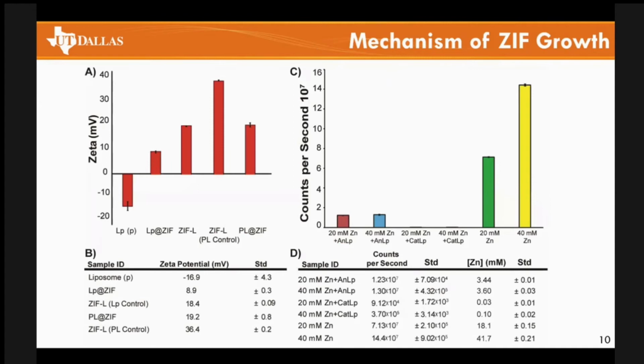Okay. So the next question that we wanted to address with this project was, okay, we have shown that we can easily encapsulate these materials in the ZIF coating, that they are indeed protected. However, we wanted to determine what exactly was promoting the ZIF growth around these materials. So we ran zeta potentials and ICP-MS, and we came to the conclusion that the negative surface charge on the liposome and the positive charge of the zinc ion served as a nucleation point for the formation of these materials around the liposome. We also tested cationic lipids, and we came to the conclusion that in the presence of a positive charge, this nucleation point was not as favorable.